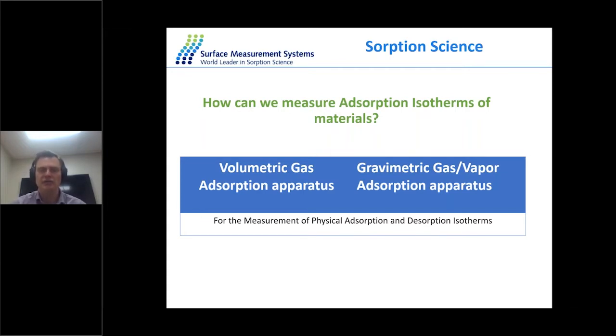And the volumetric apparatus is basically a static method. So typically nitrogen is used as a probe molecule, and you obtain data like surface area and porosity information. The gravimetric vapor sorption apparatus typically works in dynamic mode. So basically we flow the gases and vapors over the sample, and we measure the weight of the sample at a constant temperature. The gravimetric systems tend to be used more in industry. So if you want to understand the process at more relevant industrial conditions, you tend to go for gravimetric methods because they typically operate at ambient to high temperatures, whereas volumetric ones go down to 77 Kelvin.